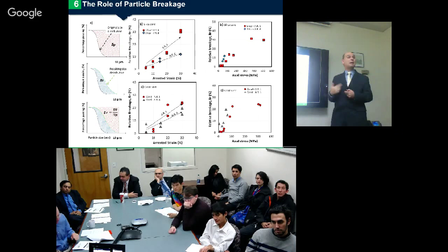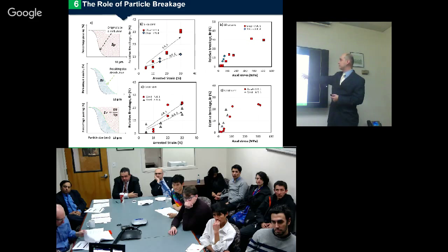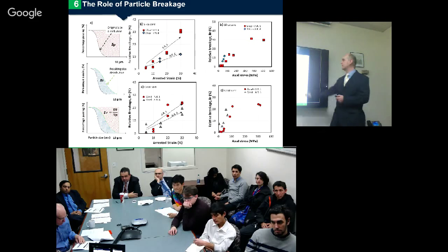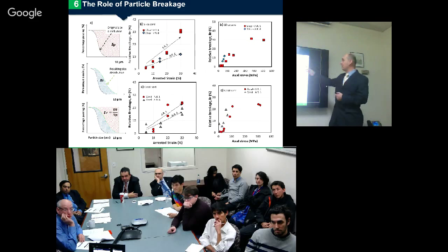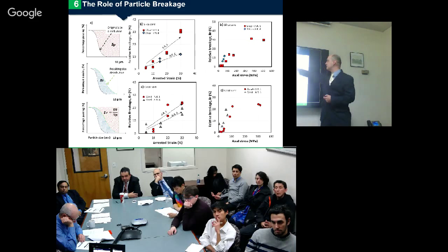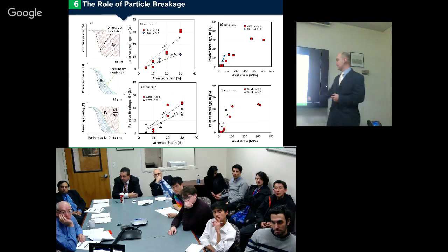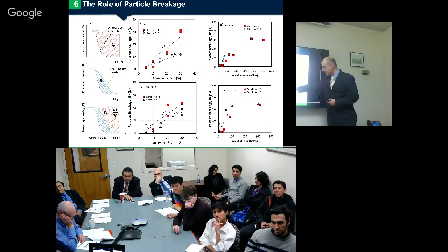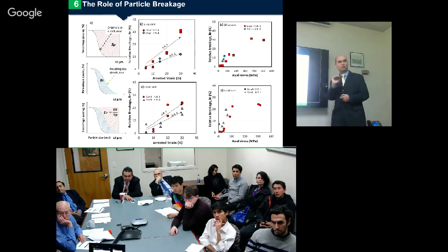But even if we keep applying more loading, from 360 up to almost or a little bit more than 500 megapascals, the damage is not evident. Now, I'm wondering what might happen if we keep going up and up and up. It might show a pattern like this. It's going to go here and it's going to go up. Something similar happens to the other material. See, after 188, we get something like this, but in this case we get a flatter response, like here.